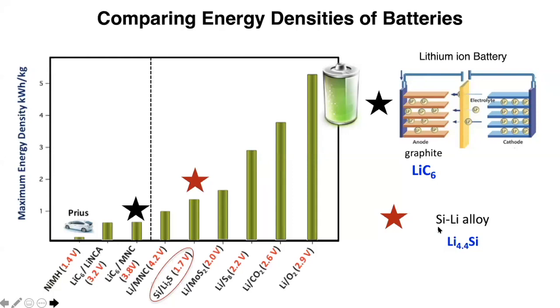And the reason for that is silicon can form alloy with lithium. So every one silicon atom can alloy with 4.4 lithium on average. So you can see the ratio is completely inversed, and a lot more lithium can be stored in silicon. So why not use silicon as the anode? Well, the problem is